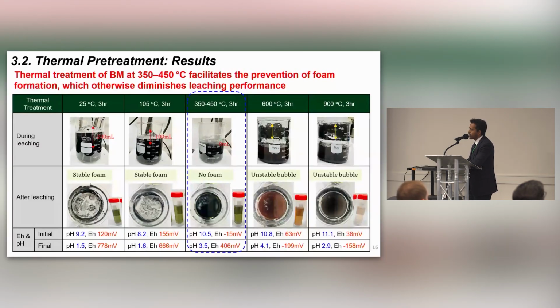And this is one of our key highlights here. We tried some pre-leaching tests in order to understand the impact of the thermal treatment. You can see if we introduce the black mass without any thermal treatment at room temperature, it generates a stable foam. This stable foam can actually diminish the leaching efficiency of the critical metals.